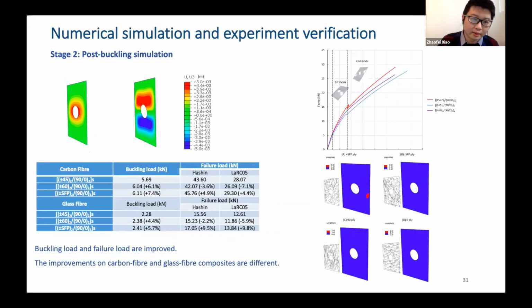Then we conduct a post-buckling simulation to understand the failure. The results show both buckling load and failure load are improved by the hybrid laminates. The improvements are slightly different between the carbon fiber and the glass fiber composites because of the difference in material properties.